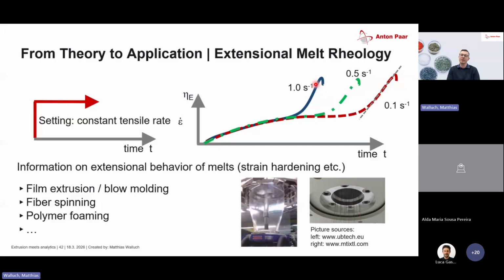This is something that you're looking for when you do processes like foaming or fiber spinning, because this shows that the material is able to stretch and doesn't collapse afterwards once it's stretched. This, for example, is the case for LDPE. If you go for HDPE, so high-density polyethylene, you don't have the long side chains that can interact. And in this case, we would have a curve that looks like this here and just goes down, because in this case, the material is not getting stiffer anymore, and it just rips off.